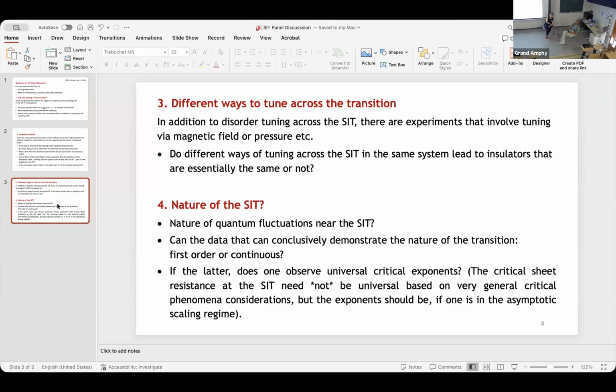On this point, I have just one more thing. Let's say I take a film of niobium, a very clean 3D film of niobium, and I measure the resistance. It will show an extremely sharp discontinuity. And following this logic, I can say that I have an extremely sharp discontinuity, but it's a discontinuity in resistance. Yeah. Resistance is not your order parameter. So this can be a discontinuity in superfluid density, which can be linked to the order. Resistance is nothing. I completely agree. So this can be linked to the energy, like a thermodynamic potential. It's the superfluid density, which would be, if you want, the mod square of the Ginzburg-Landau order parameter.